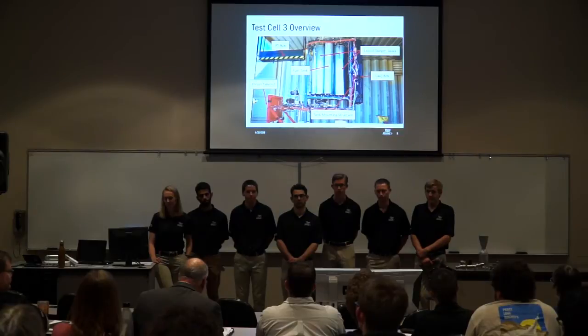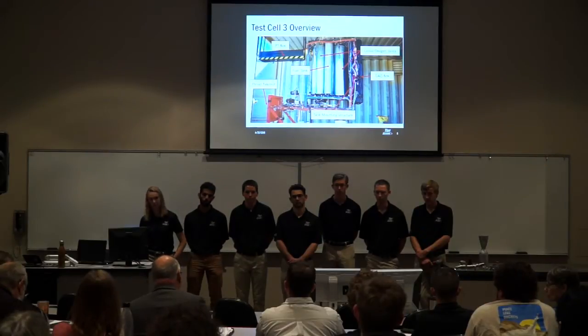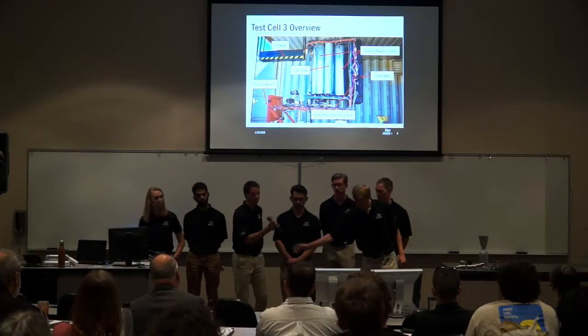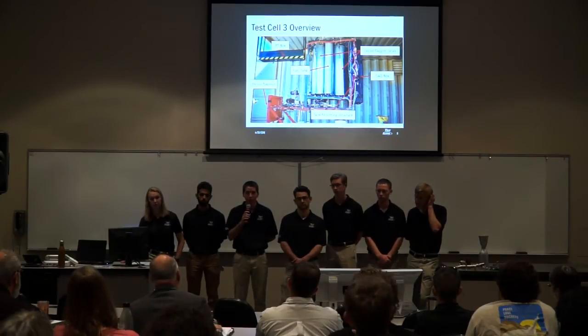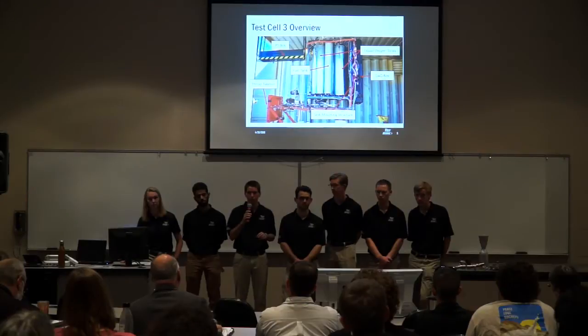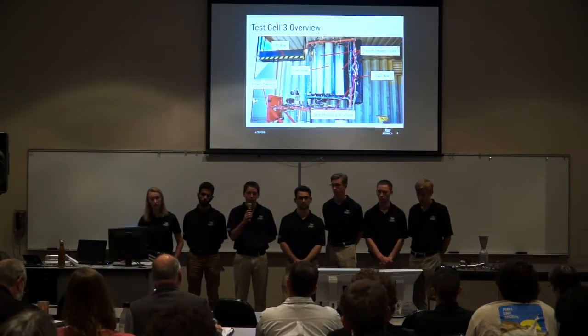Let's see. And then one more question is about your thrust chamber. About how many fire tests do you think your chamber is good for, and what types of things do you need to look at between tests? So after the first test, we measured the change in throat diameter to be about a 16th of an inch, and we saw it was about identical in the second test, and those two tests were about the same duration. A 16th of an inch is more than we need. This is faster erosion than I would like to see for a full 12 second hot fire.